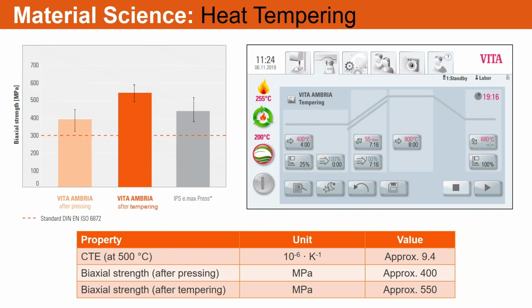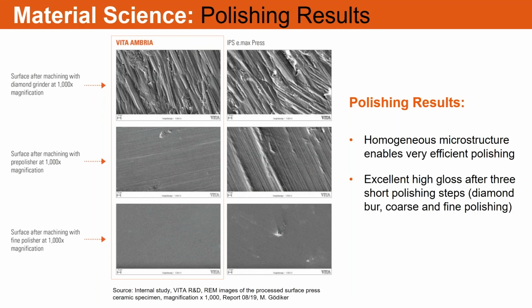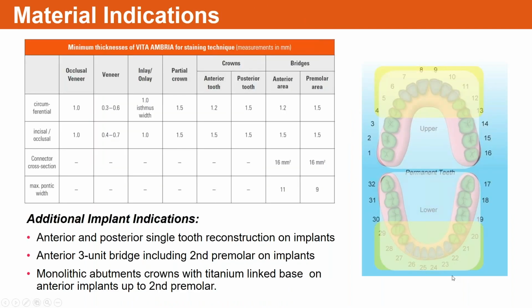which is actually about the highest press material out there after you temper it. So it's a very nice material that you can add more to it. Polishing, you know, there's a comparison with Emax. Obviously, VITA is always trying to produce any material that they do so that it's tooth-like and shade consistent, but it also has the properties of a tooth, like it will wear, polish, shine, and gloss like a natural tooth. So in the structure, by tempering it, you also bring in those crystalline structures a little bit tighter, and you can actually get a nice homogeneous gloss look if all you do is polish it after you press it.